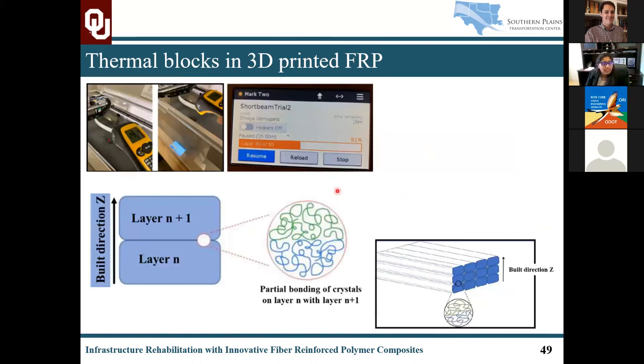If we consider 3D printing, one major advantage we have is this particular bonding of crystals, because these are all thermoplastic resins, thermoplastic spools that are built one on top of the other in terms of layers. This crystallization and bond is a very, very crucial aspect for the resulting component that we can produce. So if we affect this bond by modifying parameters like temperature and using different kinds of dampening mechanisms, this particular layer-to-layer interface can be affected.